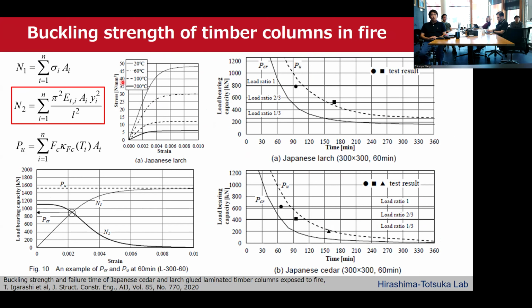These are the numerical results of the change in compressive strength and buckling strength of columns exposed to fire heating, and also including the cooling phase. Here, PU is the compressive strength and Pcr is the buckling strength. The buckling strength was calculated based on the tangent modulus theory.